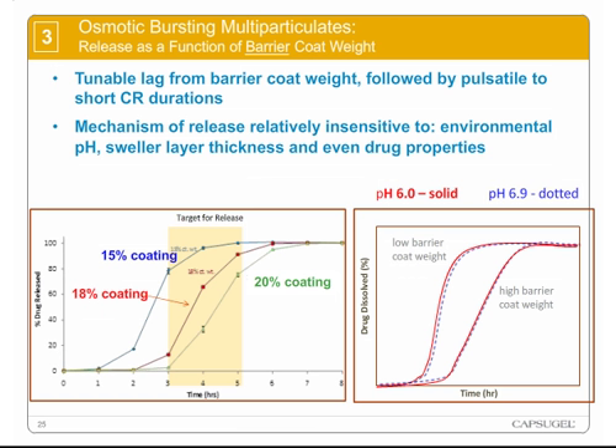The mechanism of release is also relatively insensitive to sweller layer thickness, surprisingly, even though that's the key to the mechanism of release. The swelling layer thickness is not critical usually. And even the drug properties are fairly insensitive. In this particular case, we could use 2 different salt forms of the drug, and we've also used amorphous dispersions underneath these of very highly lipophilic drugs, and seen very similar profiles to those shown on this page.